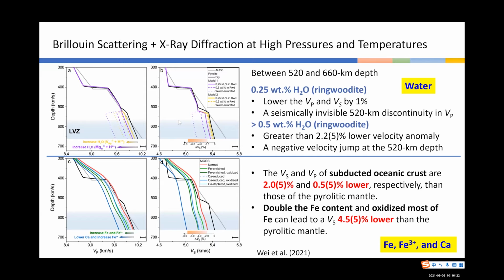The most prominent feature we see in those hydrous models is this: look at this yellow line, which means water is present in ringwoodite in the octahedral sites. In this case, if we only add 0.25 weight percent of water in ringwoodite, present in the octahedral sites, the influence of water on both VP and VS is very small. If we only look at VS, if the mantle is completely water saturated, that means the ringwoodite contains more than 1 weight percent of water.